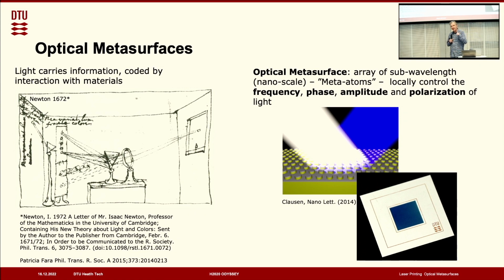So this means when light interacts with such a surface as illustrated here to the right, that is reflected on the surface, then this surface is engineered with these small nano Lego parts there, so that it selectively absorbs, in this case, the red part of the light, so the reflected light appears to be blue. And this is also illustrated in the picture to the bottom, where you have such a surface, and then you have such nanostructures with different sizes of these small bumps. So in the central part, you can see a blue circle, or sorry, a blue square, and then in the bottom right, you can see the logo of DTU, which is red.